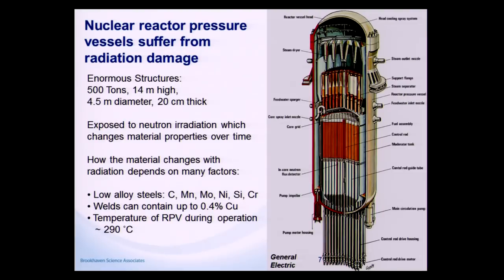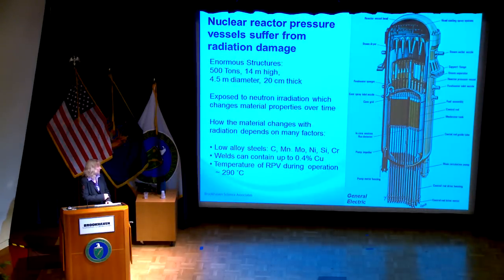So at the beginning of life, you've carefully designed your material and built it to within specification, and you have a certain material. Over time, the microstructure of the material changes. So 20 years, 40 years, 60 years, you no longer have the same material that you started with at the beginning of life. And how this material changes through time depends on many factors. In steels, it depends on the chemistry, so there are many alloying elements in steels. In addition, it depends on the product form.